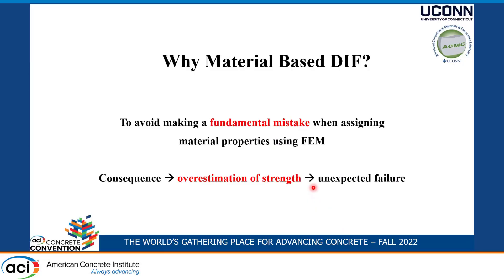Why do we do this material-based DIF? In summary, it's to avoid making a fundamental mistake when assigning material properties to FEM — finite element analysis methods — because if you do so, you would potentially overestimate the strength of UHPC, which could then lead to unexpected failure.